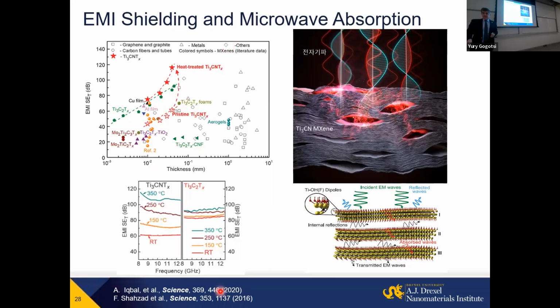With MXenes, in this paper, we published the first paper in 2016. It aligns with much more conducting copper or gold and aluminum, but allows us, remember, to make 1 to 2 micron films, which gives you about 50 decibel shielding. And 50 decibel basically means 99.999% of signal reflection. But with metal, you cannot make a 1 micron freestanding film. You take 10, 15 micron foils usually, and with MXene, you can take 1. So it was a really big breakthrough in the field.